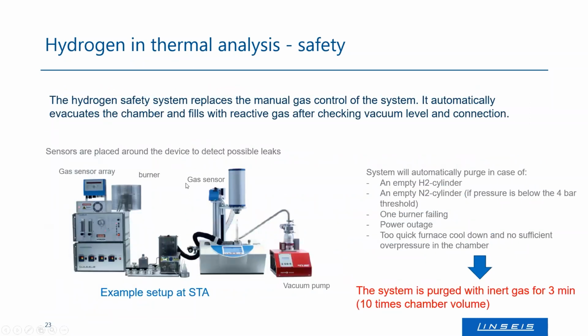What it does in detail, and you see it here coupled to an STA system, you have a sensor array in the system, and this sensor array is connected to gas sensors around your system, within your system, and in the environment. So you can monitor hydrogen leakage in the system, at the system, around the system, and in the room. And once these sensors detect a hydrogen leak, or there is an empty gas cylinder, even if it's the inert gas cylinder, or if the inert gas is below the threshold, the system will stop the hydrogen flow, close the bottle, flush your system, bring it to a safe temperature, bring it to a safe state, no matter